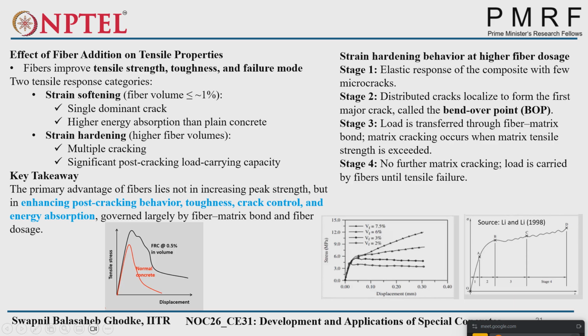Here you see the fiber content goes on increasing. First, you can see up to two. This one is 2%. It may be the critical value between strain softening and strain hardening. Below 2%, the graph will come down like this. Above 2%, you will see the graph going up like this. That is called strain hardening, which is more useful in the case of flexural specimens.